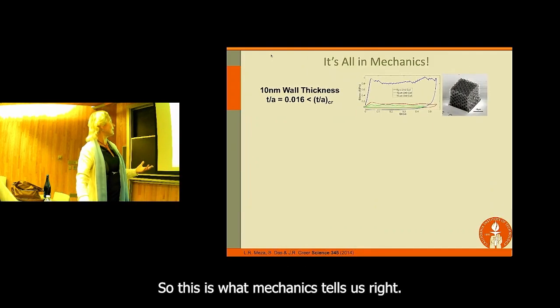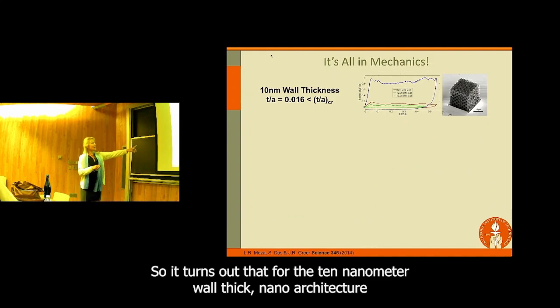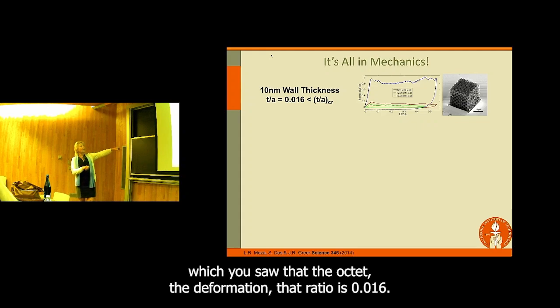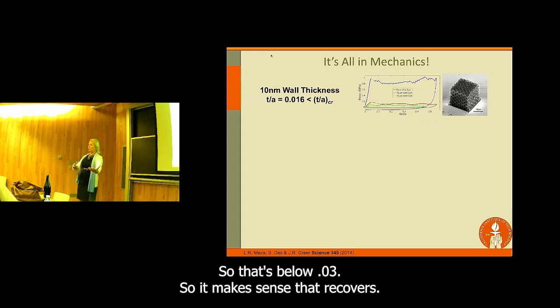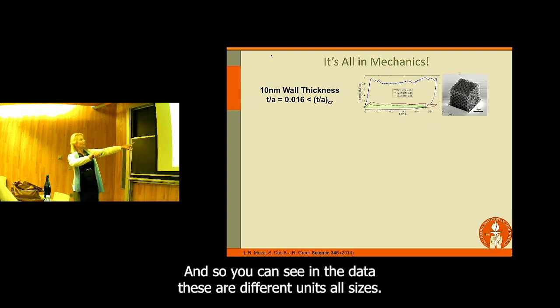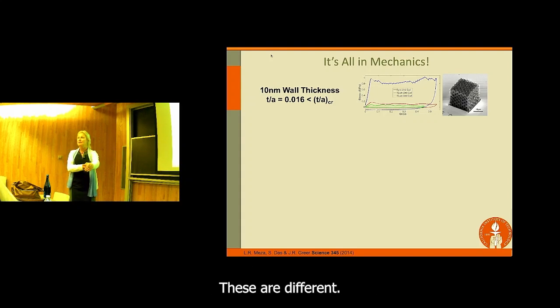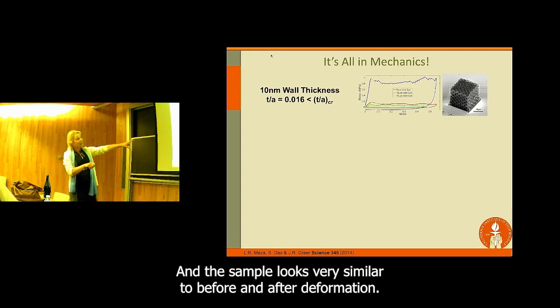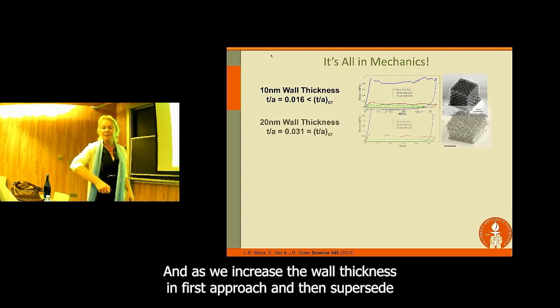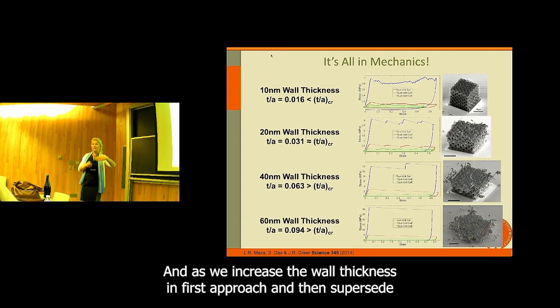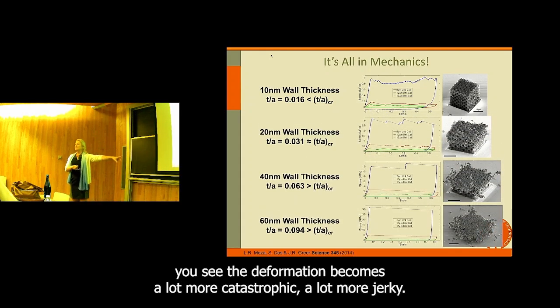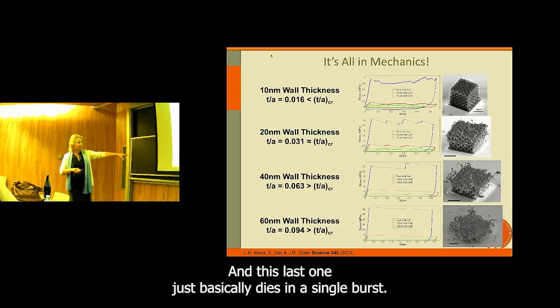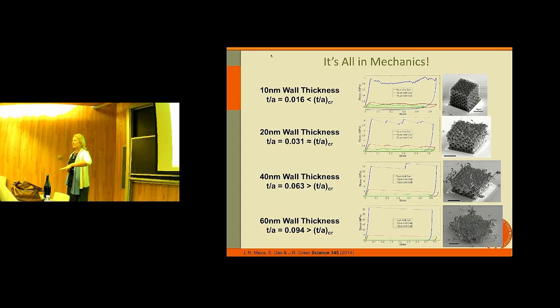So this is what mechanics tells us, right? It turns out that for the 10 nanometer wall thickness nano-architecture, which you saw, the octet, that ratio is 0.016, so that's below 0.03. So it makes sense that it recovers. And you can see in the data, these are different unit cell sizes, these are different relative densities, and you can see it recovers every time, and the sample looks very similar before and after deformation. And as we increase the wall thickness and then supersede that critical thickness, you see the deformation becomes a lot more catastrophic, a lot more jerky, and this last one just basically dies in a single burst.